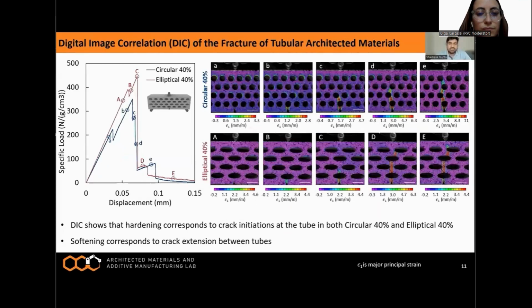To better understand the crack propagation in the tubular architected material, we carried out digital image correlation on the fracture test. You can see that following the crack initiation from the notch, the softening corresponding to the crack extension in both circular and elliptical designs was observed. On the other hand, each hardening corresponded to the initiation of the crack from the tube. These experimental findings from DIC validate the hypothesis of the stepwise cracking.